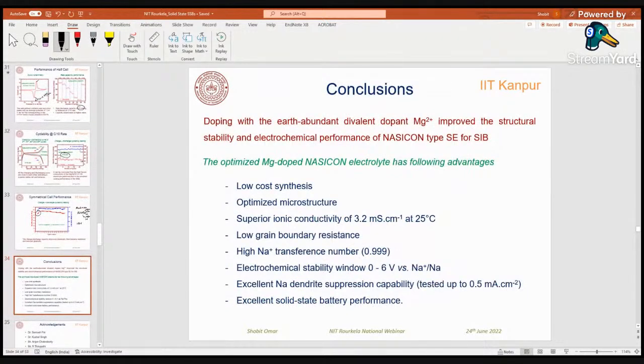So this is the conclusion of this work about the electrolyte. We have used magnesium, which is earth abundant and cheap, and that can be used for solid electrolyte in sodium-ion batteries. Of course, there are 2-3 other reports which say that one can improve the conductivity to 4 to 5 millisiemens per centimeter by using scandium. But scandium is costly compared to magnesium, and it's not easily available as well. So magnesium is the way forward for the Nasicon electrolyte.